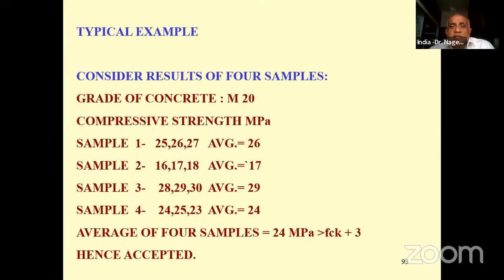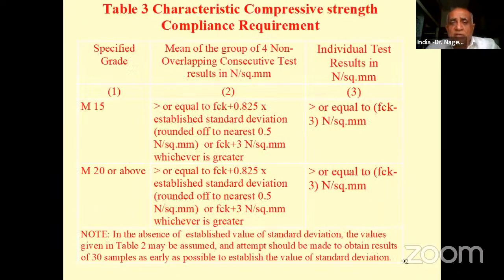So you look at this particular example. In this example, you can see sample 1, 25, 26, 27. Sample 2, 16, 17, 18. Sample 3, 28, 29, 30. Sample 4 is 24, 25, 23. So average of 4 samples, 26, 17, 29. Average of 4 samples is 24 MPa, which is more than FCK plus 3 for M20 grade of concrete. This concrete is accepted. So like this, you have to look at this requirement.